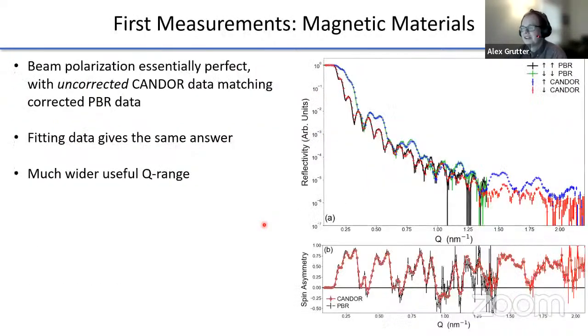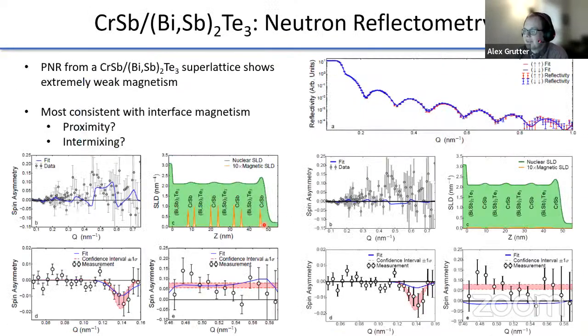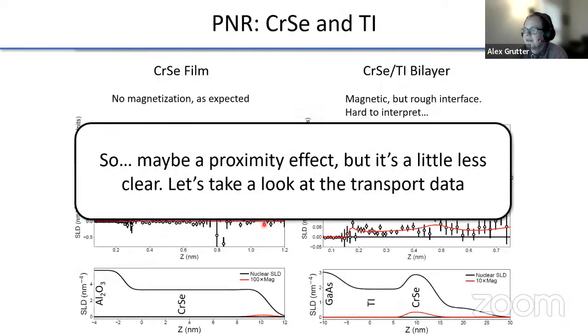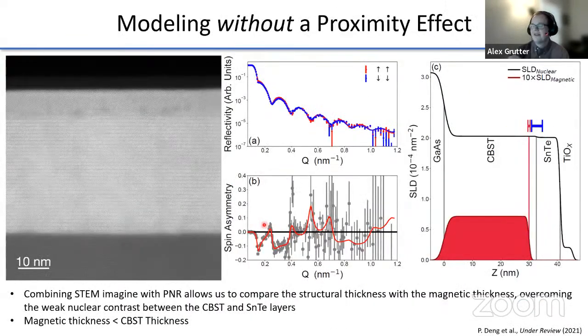And so our collaborators, I want to give a shout out to Megan Holtz, who did the TEM measurements for us. We were very nervous about this, and we had her check a number of different spots on the sample to get the thicknesses. And so the error bars, the range I give right here, is a 95% confidence interval based on the statistical sampling of the various points on the surface. So yeah, we're super duper nervous about that, and you can get into real trouble.